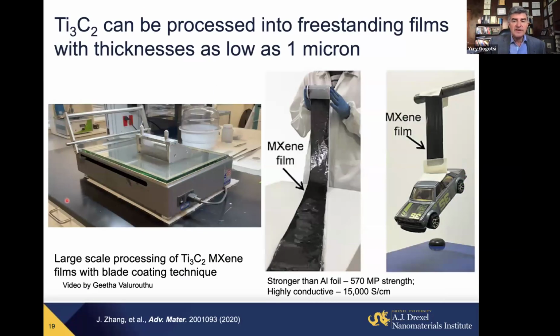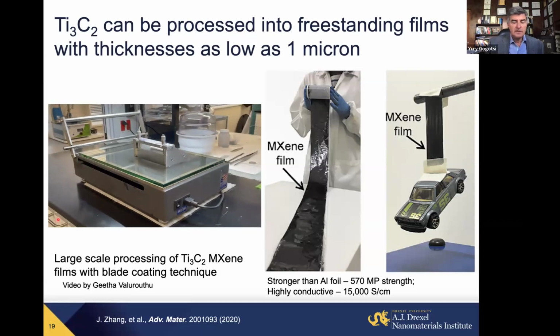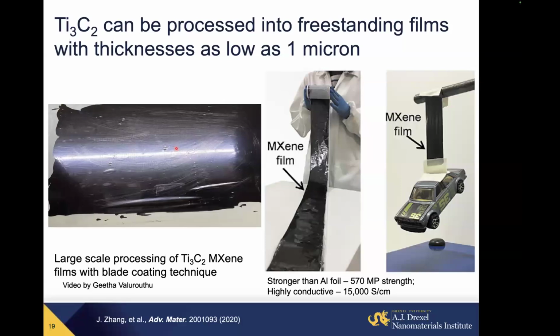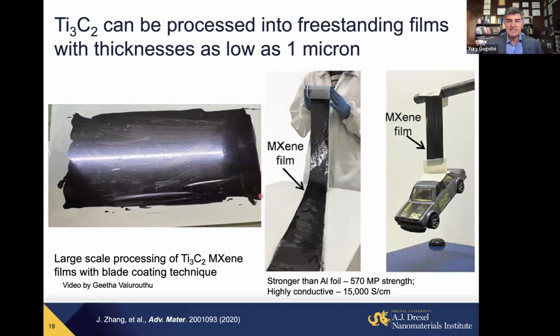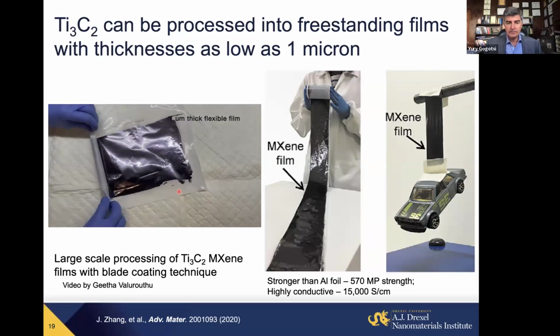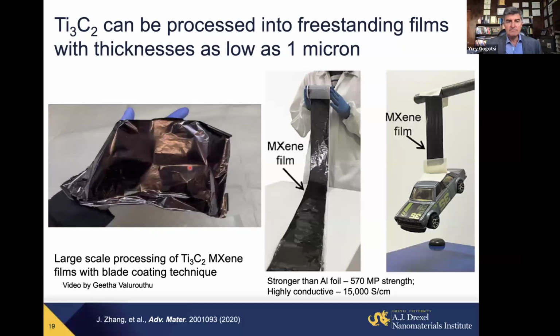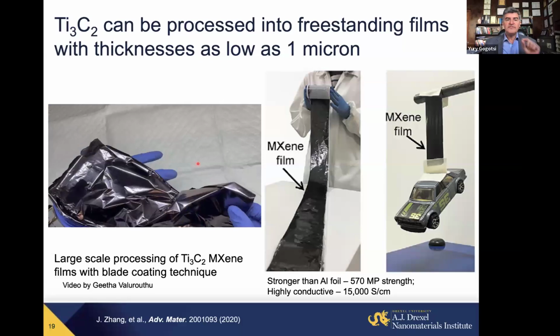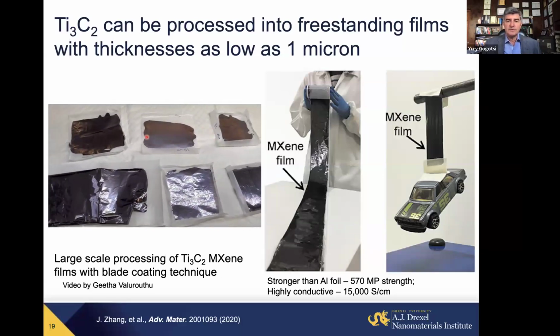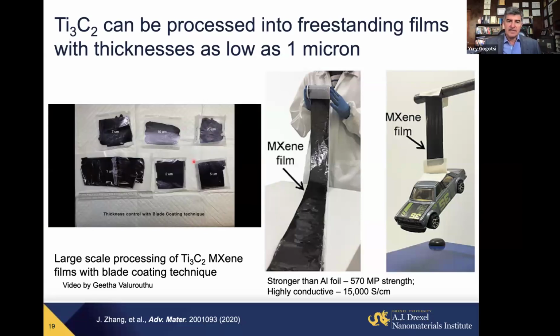And again, the process is very easy. You take this concentrated solution, and you spread it, as you will see here, on the surface, and let it dry. After that, you can separate this 1 micrometer thin film. You see, it is just 1 micron thin, 10 to 20 times thinner than metal foils people use. You can, of course, make it thicker, 20 microns, 10 microns, like metal foils. But what is important? After just drying, this film has strength at least the same or even higher than aluminum foil. For example, you can make a current collector for a battery 10 times thinner.